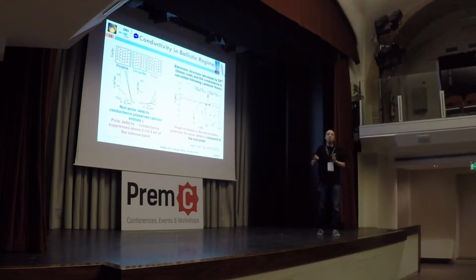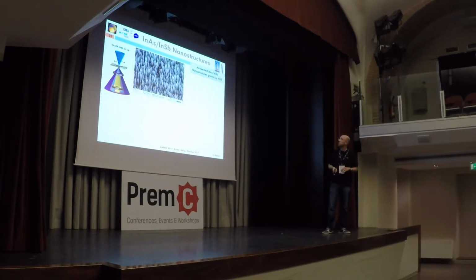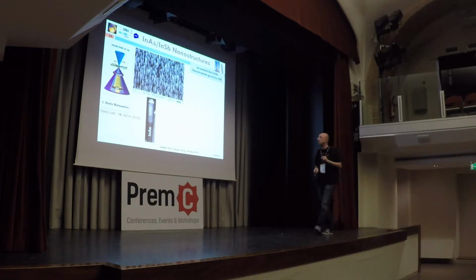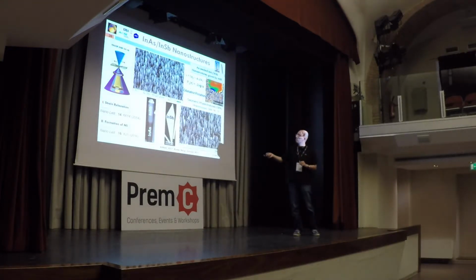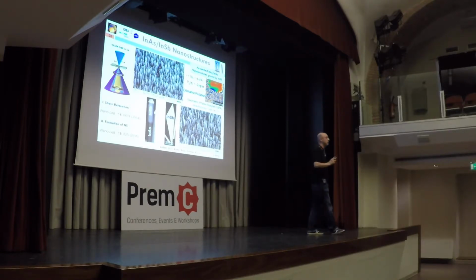So if we want to have a ballistic regime of the conductance, here the different carriers will be scattered, here the electrons, here the holes, and then they will not trespass. So in this case, an inversion domain just in the middle will destroy the electronic properties of this material. This is why it's important to understand what we have at the atomic scale and then understand what is going on here. So now I will show you another example on how we can change from the formation of one nanowire to the formation of this really nice nanomembrane only by creating one single defect at the beginning of the growth.